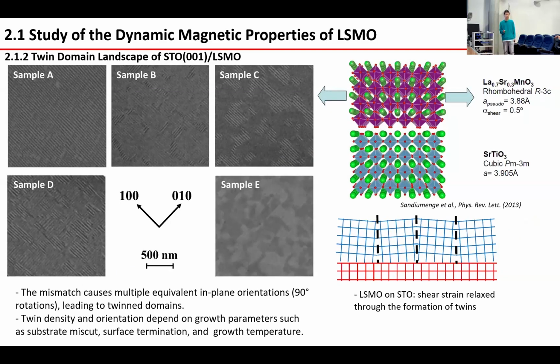We are measuring the electron backscattering image from the SEM, where sample A shows a microstructure of single twin domains, while samples B, C, D, E show two in-plane orientations of twin structures. So what causes them? It's due to the relatively low symmetry of the LSMO with rhombohedral structure having to adapt on the STO with high symmetry, a cubic structure. It will form twin structures.